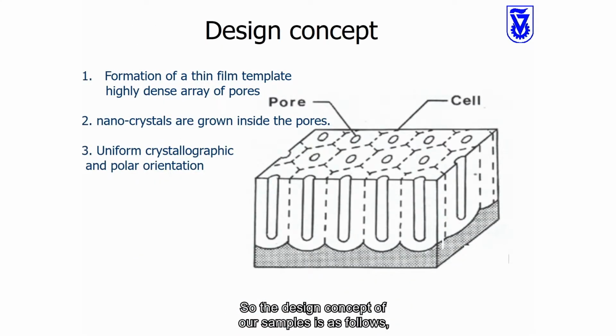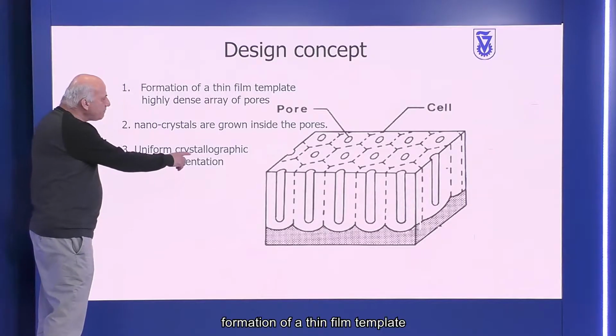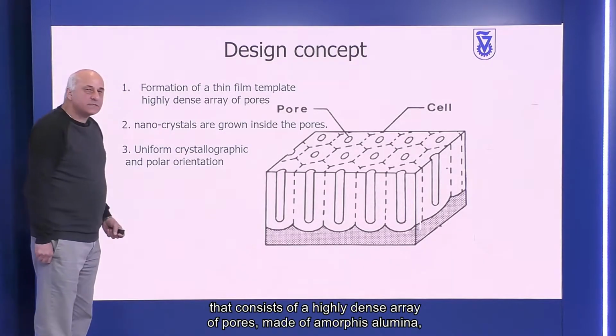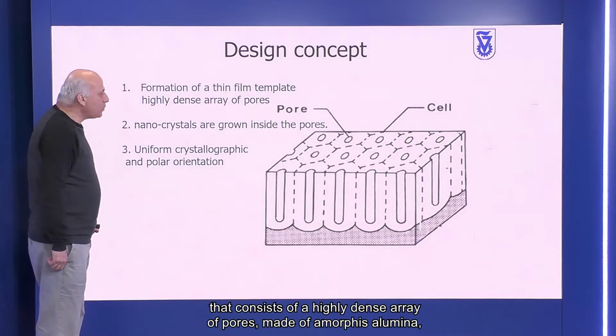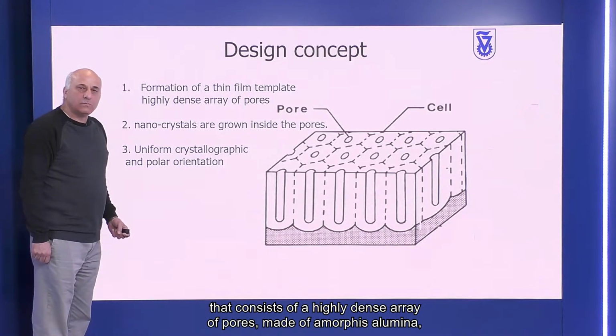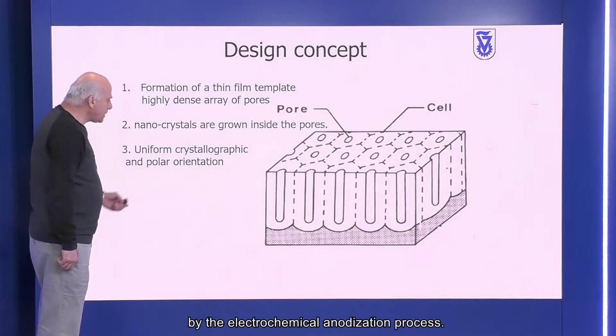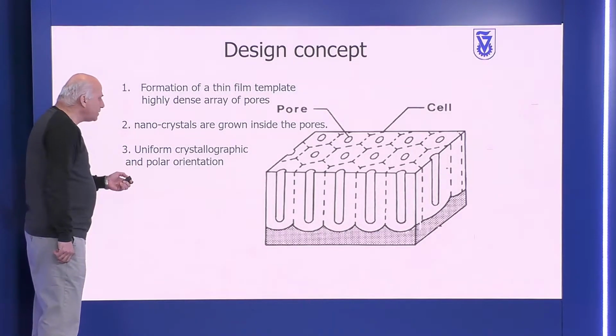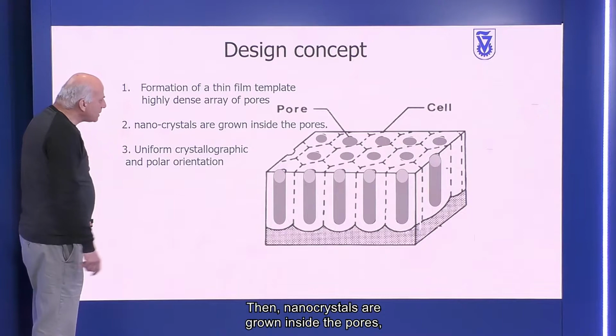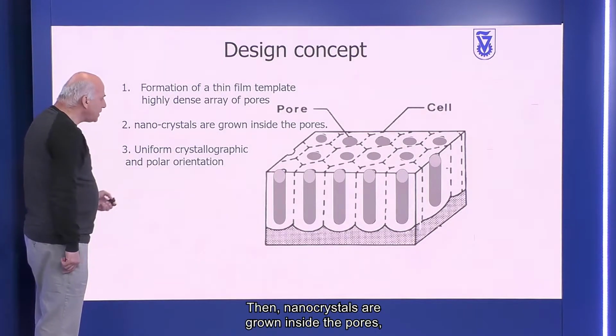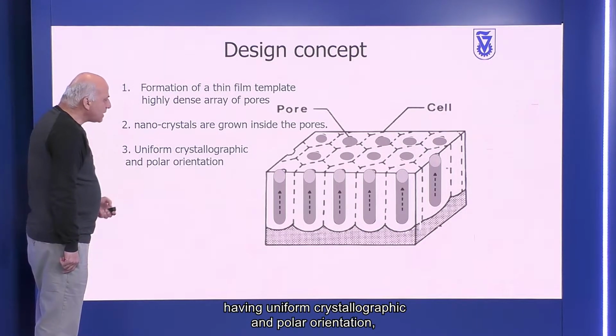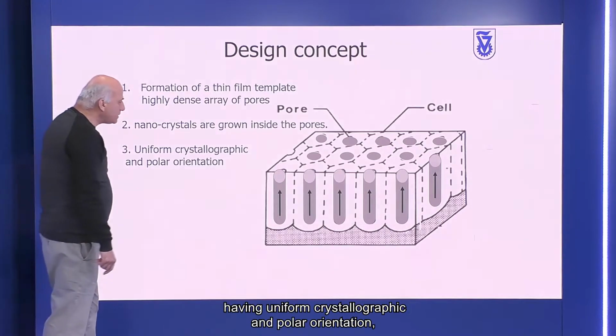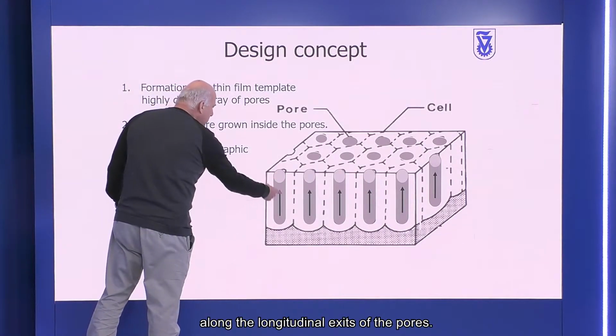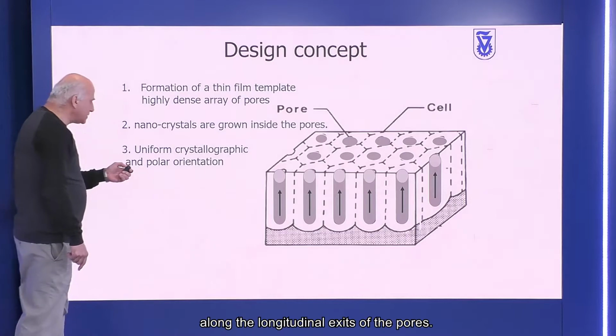The design concept of our samples is as follows. Formation of a thin film template that consists of a highly dense array of pores made of amorphous alumina by the electrochemical anodization process. Then nanocrystals are grown inside the pores, having uniform crystallographic and polar orientation along the longitudinal axis of the pores.